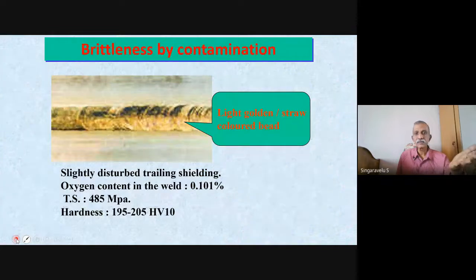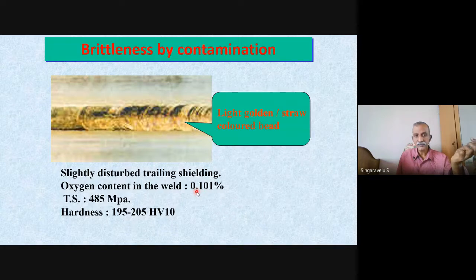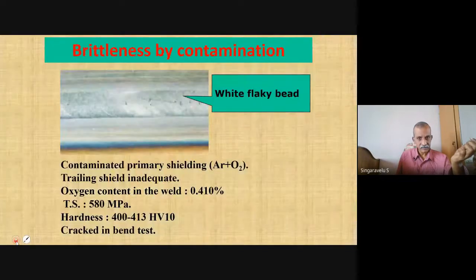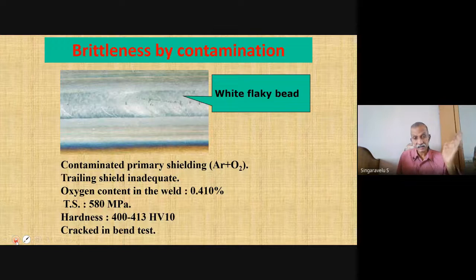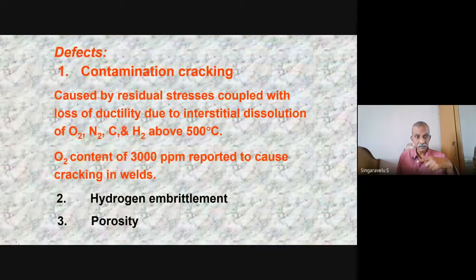This is another view. Light golden straw color bead, right? The oxygen content is 0.1. It causes brittleness because of these corners. So this is another one. White. The trailing shield is not sufficient. It has failed in the bend test because of this brittleness. Okay.